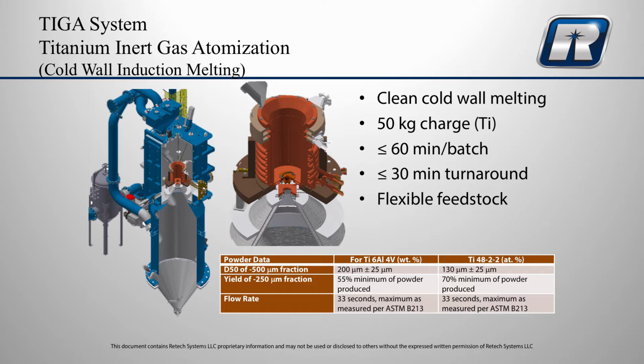And then there's an approximate 30-minute or so turnaround time for the system. The ability for this system is primarily its ability to melt a wide variety of feedstocks. Some of the powder data is shown here in the lower right-hand side. The powder for 6-4 tends to be somewhat coarse. The powder for 48-2-2 can be somewhat finer, and depending on how you look at your yields, what we've just put is the minus 250 fraction, the yields, and then the resulting flow rates for the powder.